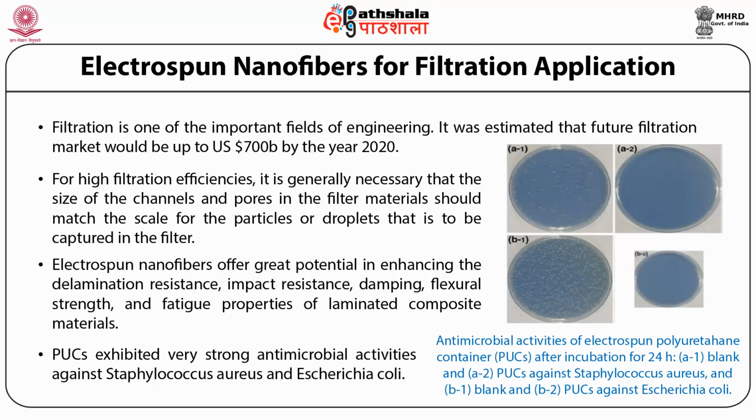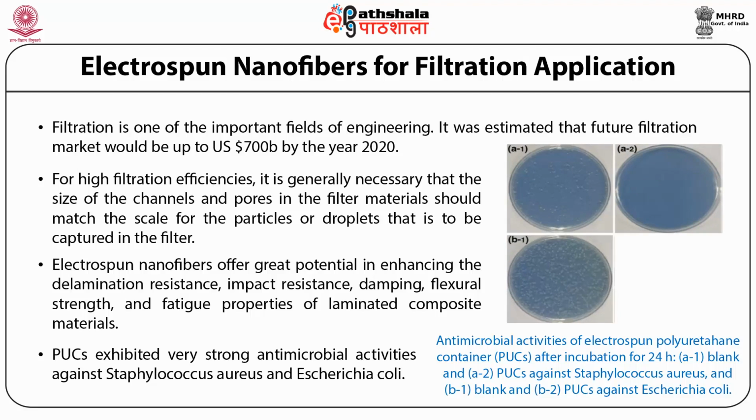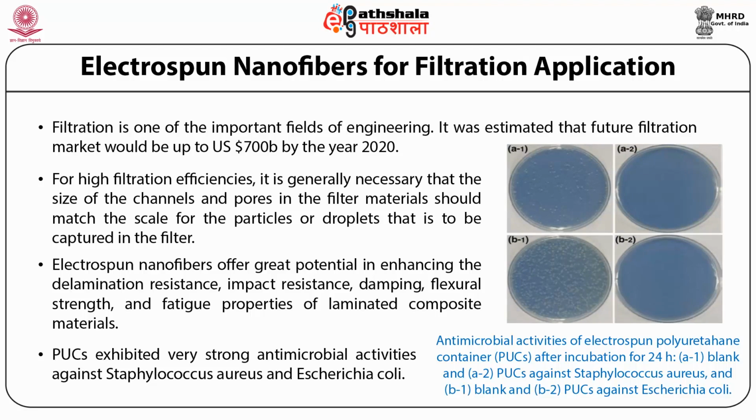Another report suggests the separation of micro and submicron polystyrene particles of 0.5 to 10 µm from water based on electrospun nylon 6 nanofiber with a diameter of 30 to 100 nanometer.